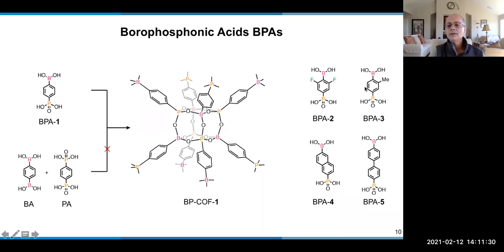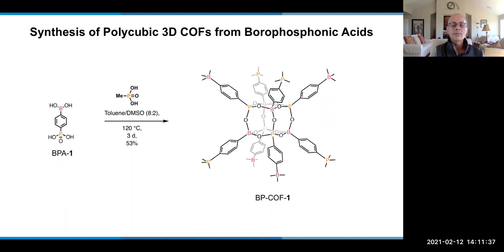And you can functionalize the building units, and the chemistry is fairly versatile. You can expand the building units and still make the cubic forms. The thing that reticular chemistry provides you is the right conditions under which to crystallize this, and the addition of what we call modulators, like the aniline in the case of imine, that can modulate the kinetics of the system so that you can crystallize, make crystals of these extended structures.